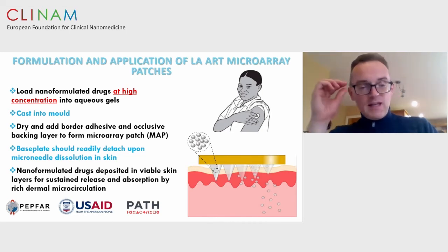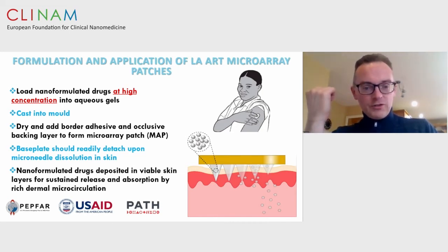So you should dry the needles and then have a border adhesive and an occlusive backing layer to form the patch. And the base plate upon which the needles are formed should either dissolve on the surface of the skin or, better still, readily detach after a short wear time to leave the needles and their drug content beneath the stratum corneum. So we can then have sustained release.